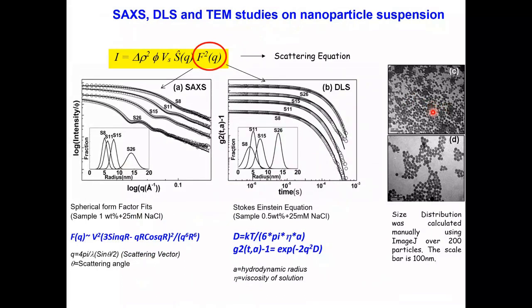Now, once electron microscopy gave me the information that this is a spherical nanoparticle, I can go back and fit the entire data, the symbols shown in open circles, with a spherical model. I had some information from the TEM, although TEM did not give me average information. TEM gave me information about only some thousands of particles, but there are zillions of nanoparticles in the solution. So whatever size information I have obtained here is the average value, and it corroborates very well with the dynamic light scattering studies.